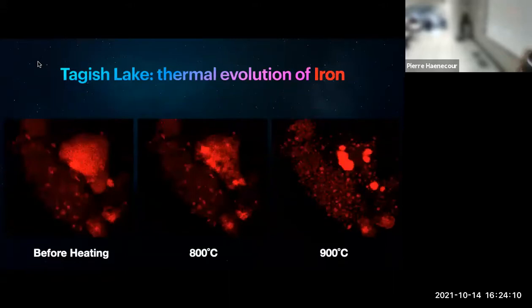And then if we look at the iron, which is the most interesting in that aspect, you can see that between room temperature and the flash heating, there are clear differences, but there is no clear evidence yet for those nanoparticles. We can just see there is some rearranging of the iron, but then going to 900 degrees, you can clearly see that now you form those iron nanoparticles. So basically, all those bright particles that you see all around the sample are iron metal. It might not be pure iron metal, because if you look at the silicon signal, you actually have a significant amount of silicon in it. We couldn't quantify it yet. We are working on getting quantification of the silicon signal, but it's mostly iron nickel particles.